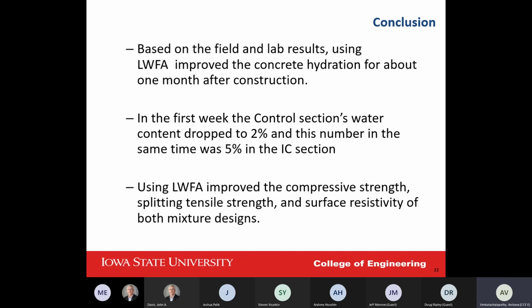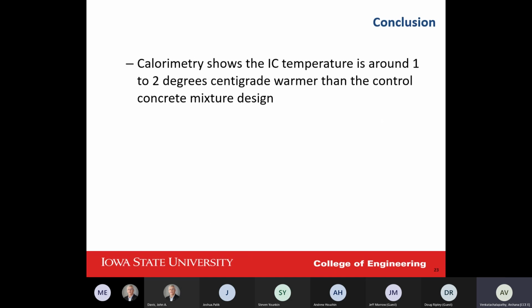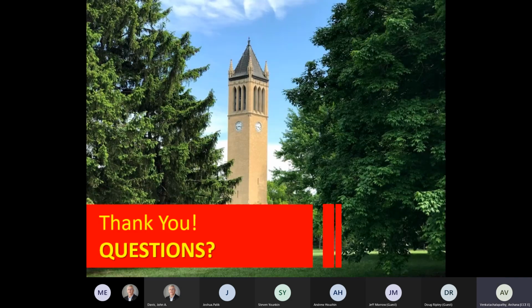Okay, on the last page, and sorry if I talk too much. Technically, using the lightweight fine aggregate improved the concrete hydration about 1 month after construction. And after that, we can see the water content dropped to 2%, and this number in the same section for the internal curing section was 5%. And using lightweight fine aggregate improved the compressive strength, or just the mechanical properties altogether. Also the calorimetry shows that we are seeing between 1 to 2 degrees centigrade warmer than control concrete when we use the lightweight fine aggregate. That means we are having a higher hydration degree. Thank you.